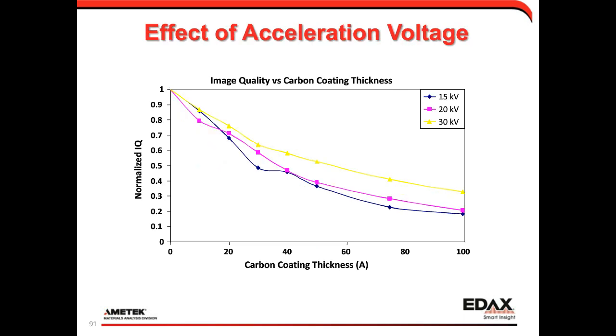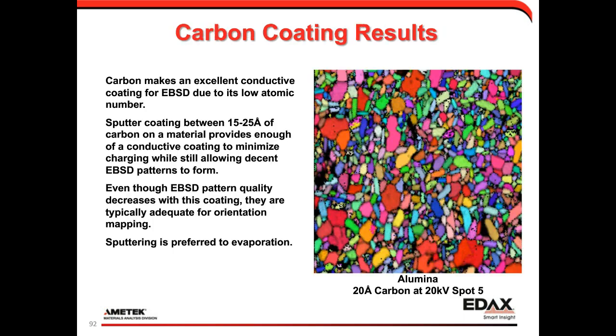And sometimes with coatings, you can go to a little bit higher voltage, so it punches through that coating a little bit more efficiently. You'll get a little bit better pattern, but it doesn't make too much of a difference. Of course, the other thing you'd want to make sure you do with a carbon coating is you want to make sure you get enough material that you can dissipate charge while minimizing any EBSD pattern degradation. Even though your pattern quality will go down a little bit, they're typically going to be good enough for your orientation mapping, but be aware there is some pattern decrease.